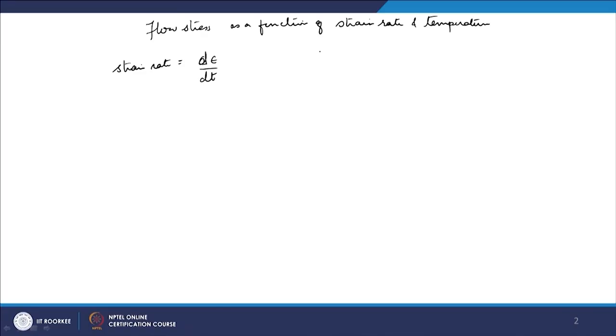So, the earlier flow curve which I showed you in the previous lecture, you can consider that all those flow stress curves you will see in a material at a temperature which is less than 0.4 of Tm. So, what is Tm? Tm is the melting point of the material, and of course, you have to take it in Kelvin. Okay. So, for example, the melting point of the material is, suppose, 1000 Kelvin. Then, if you are deforming the material at lower than 400 Kelvin, then you will see the flow stress curve which I showed you in the previous lecture. But if I am deforming at a temperature which is more than 0.4 of its melting point, so let us say more than 400 Kelvin, then you will see the effect of temperature also on the flow stress curve.